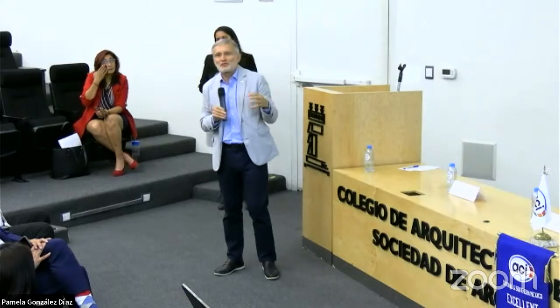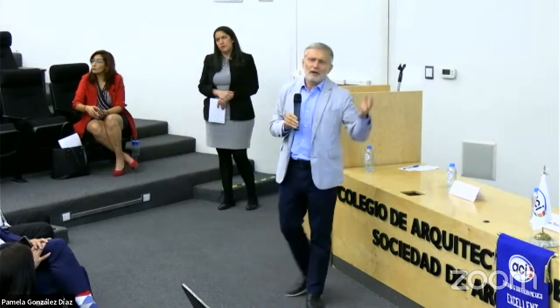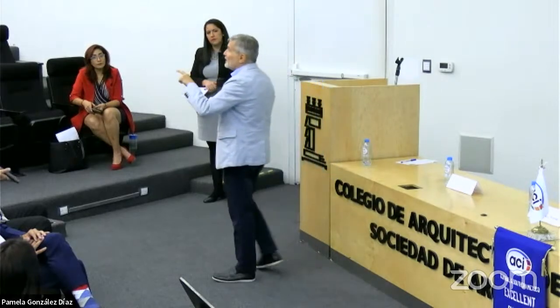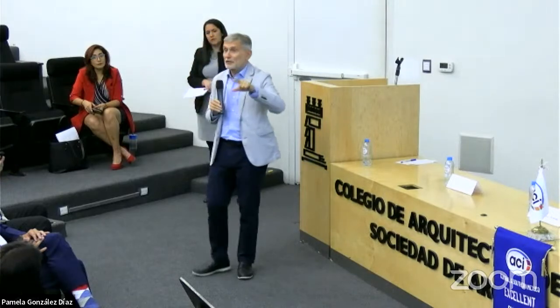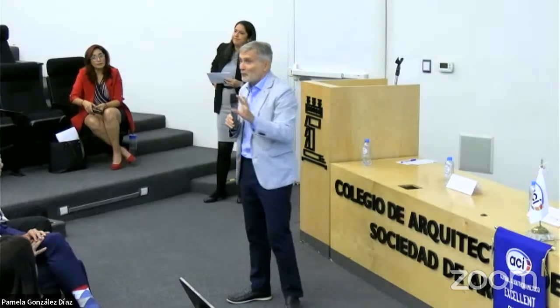So glass obviously is much cheaper. We would like to use it whenever we can. Well, actually, for example, we have done some piles, also pre-stressed concrete using glass, but we stress them at 30%, 35% actually to be correct in terms of their ultimate. And we do what we call mild pre-stressing, which economically could be very advantageous also because it's much easier to pull the tendons. By the way, in that case, the low modulus is a blessing. The precaster loves it because when we pull a GFRP tendon at 30% or 35% of ultimate, it is the same elongation of the steel strands. So they don't measure the force, they measure the displacement of the head.